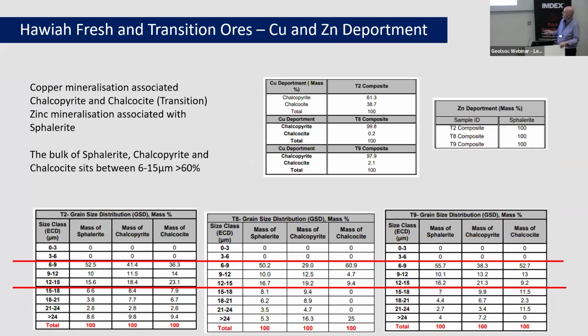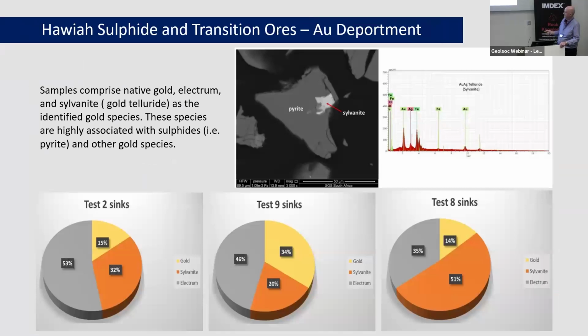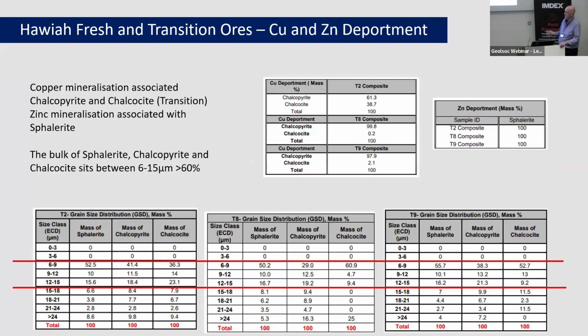This number in here, you're looking at microns, 6 to 9 microns. Standard grinding procedure for a flotation plant is 75 microns. Metallurgists, they get the ump if you have to go below 100 microns normally, but 75 microns is generally sort of the number. So even if you ground to 30 microns, and below 30 microns, it's considered a slime. Slimes don't float. So when you're looking at that, you know you're in for a hiding. So again, this should be part of your exploration procedures. And it's not expensive. It can be done very, very quickly.